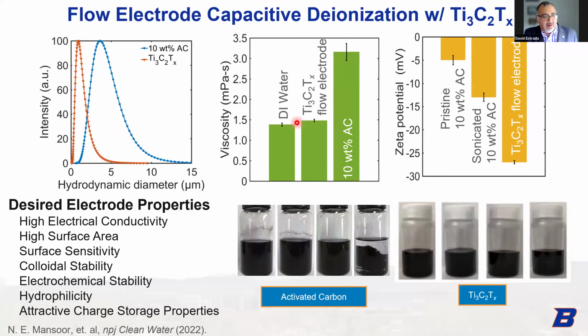Our viscosity is on the order of that of DI water, because it's largely DI water. We're only using 1 weight percent MXenes in this case. And the viscosity is a little higher on the activated carbon, but really it's the zeta potential that you can see here. We have a much larger, or smaller, I guess, more negative zeta potential with the MXenes, which makes them more stable in the DI water that we're using to flow in the electrode.